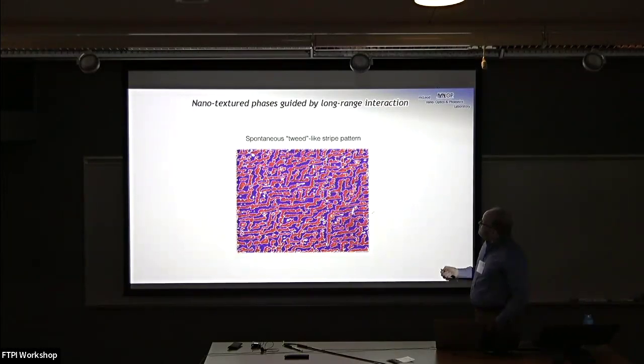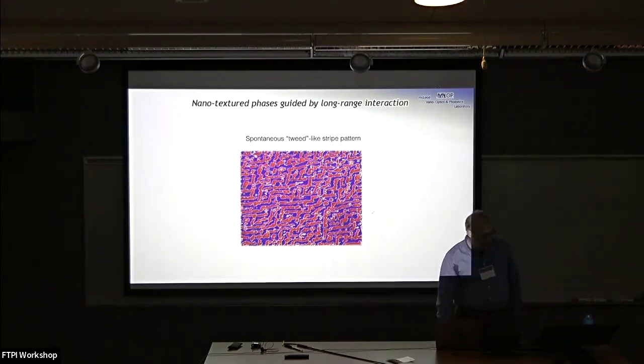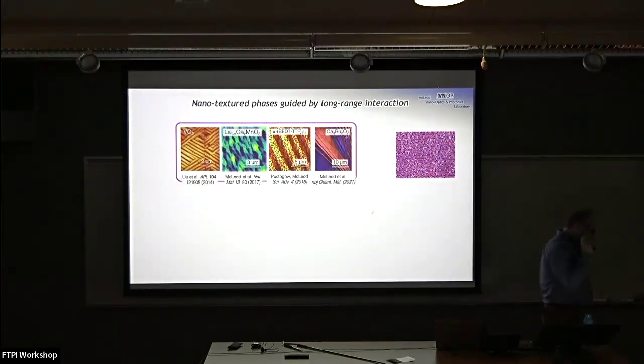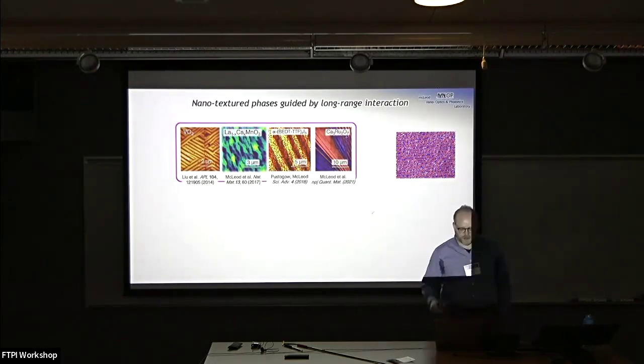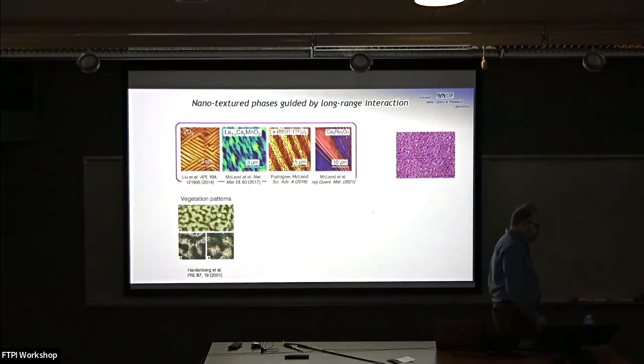So this is in the context of, let's say, steels and martensites. The martensitic transition is something that's encountered with alloyed steel, whether under pressure or otherwise. The fact that the domains, whatever they may be, take on a spontaneous texture. And this appetizer is one piece of a whole series of measurements on not totally unrelated compounds using this nano-optical technique going through a first order phase transition of some kind, ranging from manganites to Bechgaard salts to ruthenium oxides. And what all of these examples share in common is the emergence of this sort of nanotexture. So it's worthwhile to touch base with some basic physics when it comes to that nanotexture.